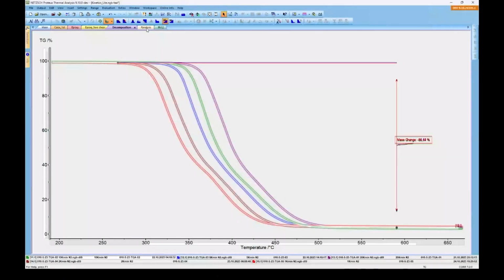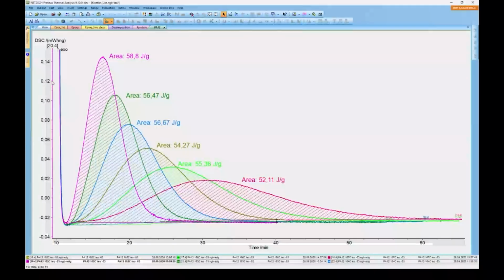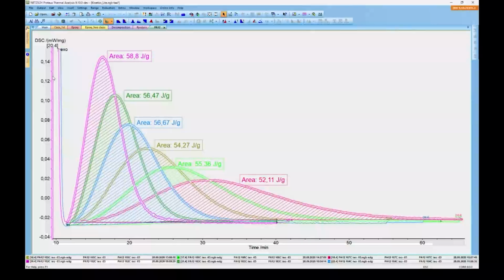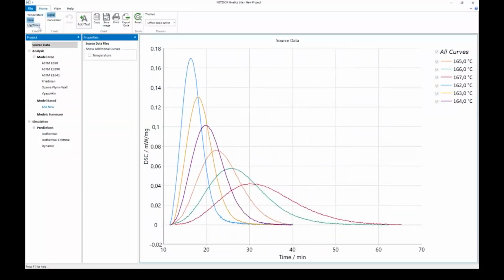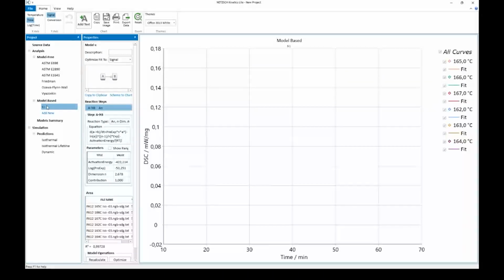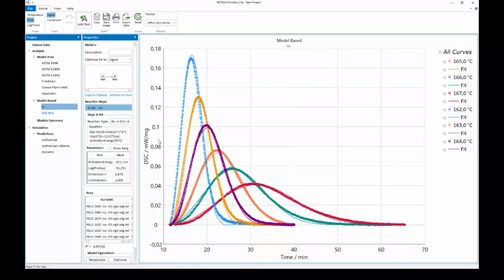We just go back, select our polyamide 12, which are real measurements at different temperatures. Here the peak area is already evaluated. We can just go to software, to Kinetics Lite, switch to time, make model-based kinetics. In this case, the software analyzed the shape of the data and found that here we have AN reaction type. It is Avrami, corresponds to nucleation during crystallization. And now we will use this data for simulation.